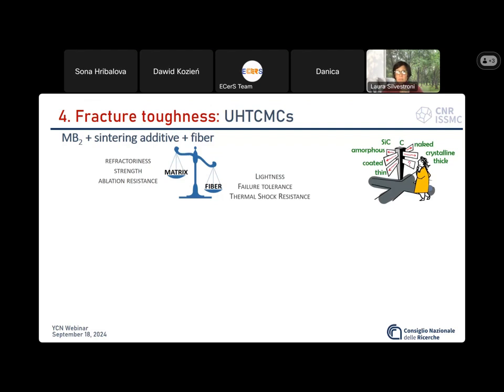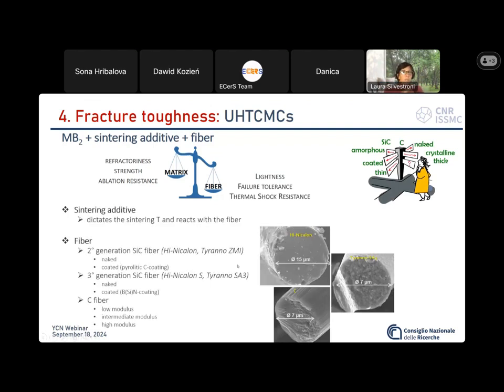So we have another problem, fracture toughness. In an attempt to mitigate the poor failure tolerance of UHTCs, research on a new class of materials that merges UHTC and CMC, ceramic matrix composites, has recently been launched and is called UHTCMC. Looking at the fiber portfolio, there is a jungle. You can vary the length, continuous or short, milled, less milled, the composition, silicon carbide, carbon, the crystallinity, add a coating, without a coating, and it's really a large playground.